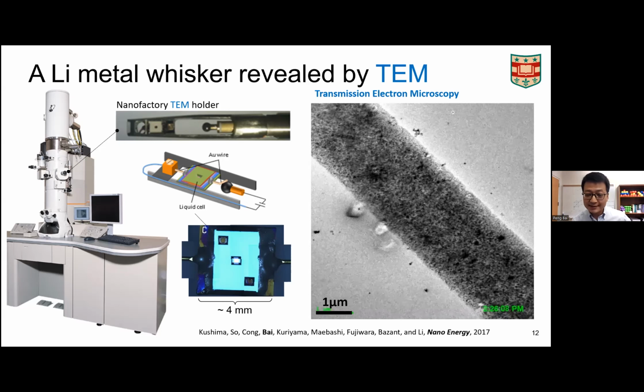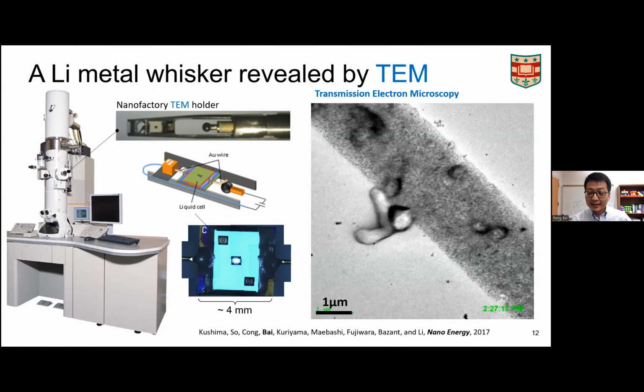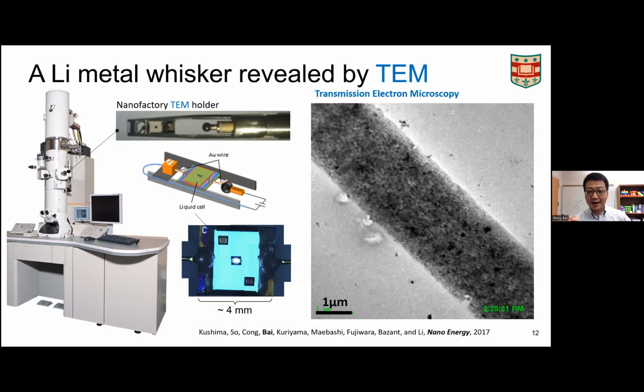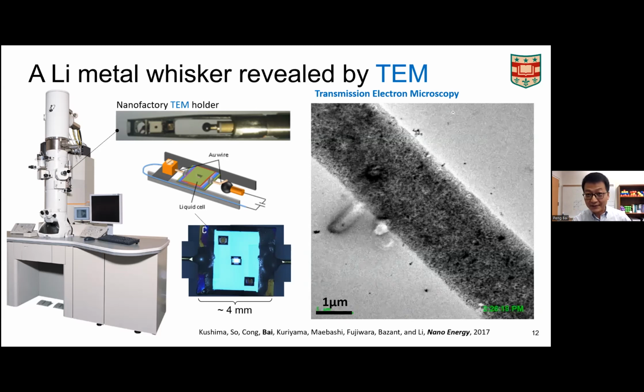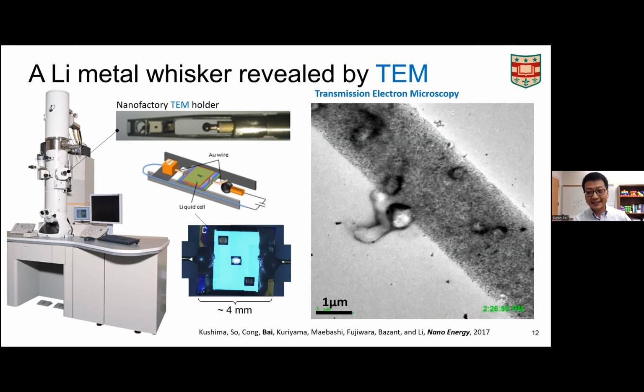So I hope you can see this, that I can replay this. There is a tiny structure emerging out of the surface, right? It's like a whisker. It's like a hair growing from the root, right? That's why I mentioned in the title that we discovered a lithium metal whisker protruding or growing out of this gold electrode, okay? When we say it is rough, it is non-uniform, the growth is really just localized and it grows like a hair, like some biological systems, right? That's quite a huge surprising discovery.